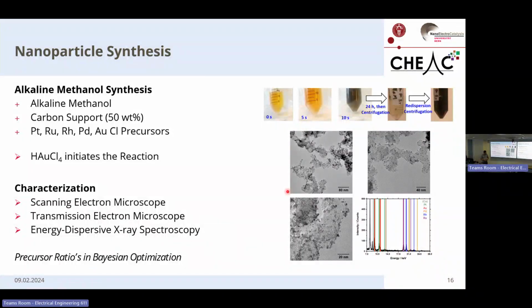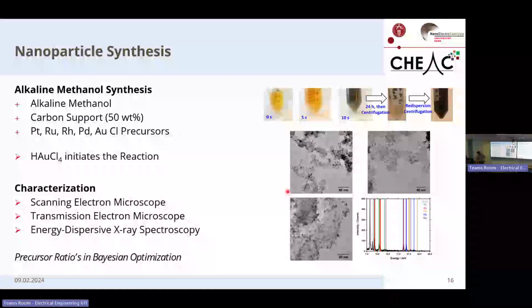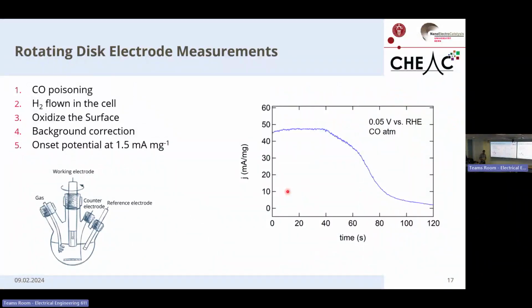So I use a synthesis method that was discovered by Jonathan Quinson, and he saw that if you take several chloride precursors in alkaline methanol, and you add gold chloride to it, it initiates a reaction, and within a couple minutes you have nanoparticles. So this is a very easy method to use, and I used it during this work. And then the nanoparticles I had to evaluate for the CO oxidation. So the way this CO oxidation potential was measured is I started off by poisoning the surface with CO, which results in the dying out of the activity, as you can see over here.